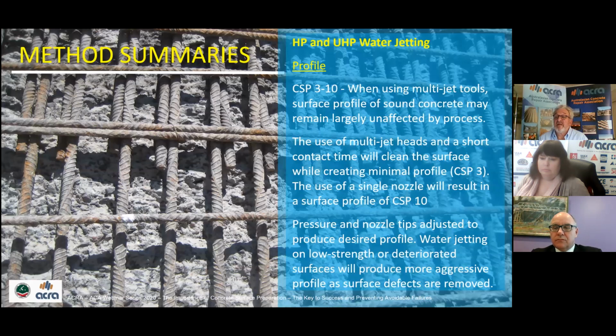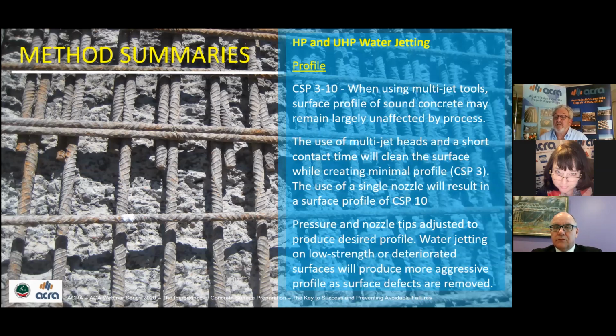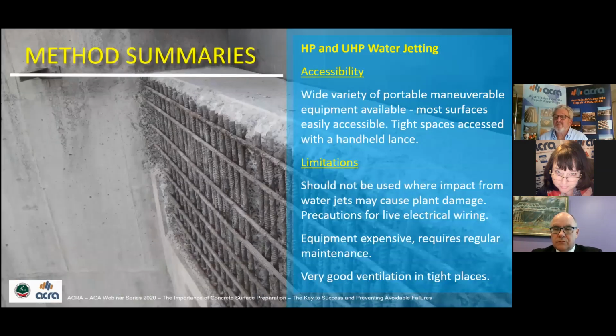The profile that we get off high pressure and ultra high pressure is CSP 3 to 10, depending once again on the concrete and how long we keep the jet there. It's horses for courses. Generally, a trial area is done to determine the pressures. The UHP water jet contractors know their rating and know what's required, and they basically do a trial panel, and we have looked at that. So that's what we need.